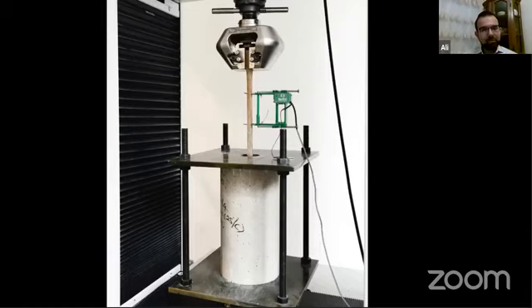the bonding mechanism between concrete and bamboo composite materials, because normally steel has a very good bond between the two materials, but we wanted to ensure that this material also has a good bond. What we did was apply some type of coatings that we got from the two chemical companies I mentioned earlier, because chemistry was not my capacity or my expertise. So I had to get that knowledge from somewhere, and got that expertise from Wacker and Rehau.